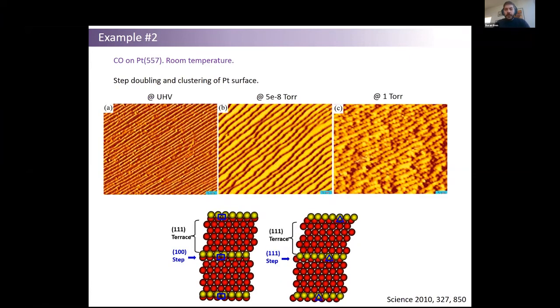Now, in 2010, something new was observed for the first time. We observed that a surface which is supposed to be very stable was actually not stable in the presence of gases. Now, in this example, again, it's carbon monoxide on platinum. This time, it's a vicinal surface. That means that you have the 111 surface, same as before, but there's a miscut of 10 degrees. So this is the illustration of the surface on the left-hand side.